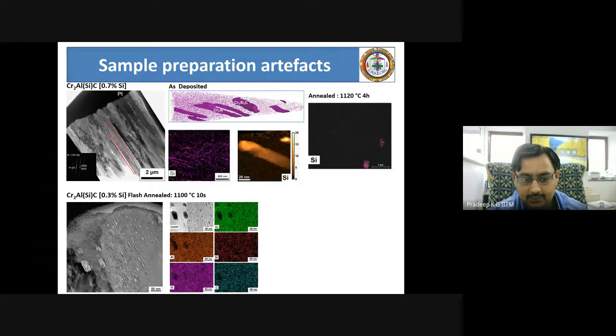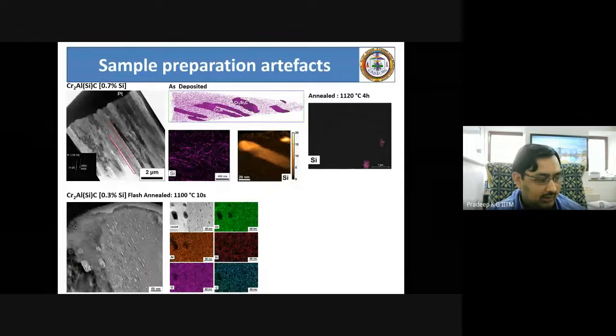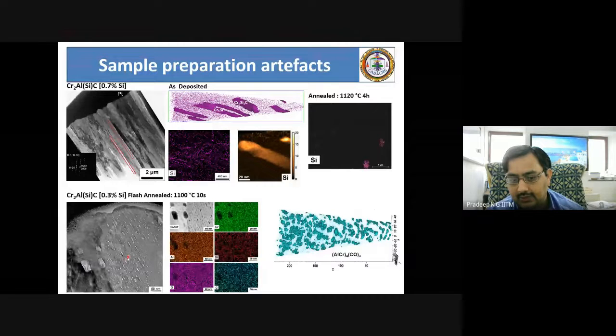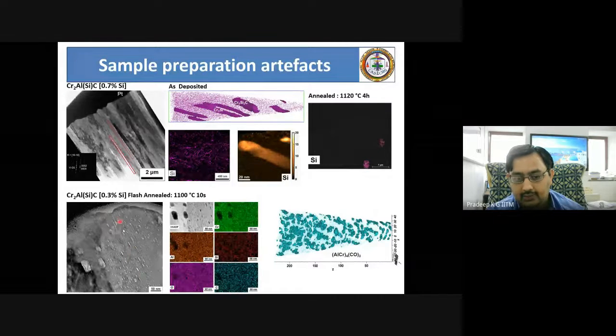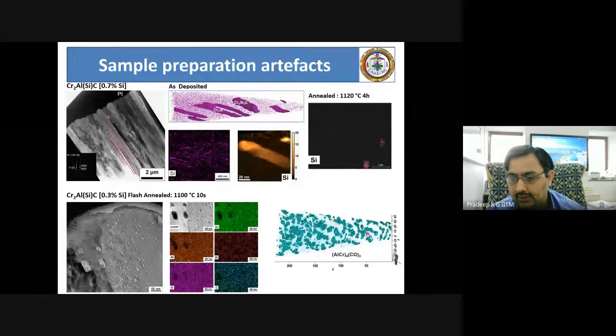Now, a similar example is at the bottom. As you see here, there are a lot of these nanoscale features visible in the microstructure of the same material. The EDS mapping indicates there is no signal coming out of these nanoscale features, which means these are all holes in an ideal way. But if you look at the same in an atom probe, you can see all of these nicely arranged columnar features visible in this order, where it is all rich in oxide content, based on aluminum chromium carbon oxide. That means when you get this material in the three-dimensional analysis, you are able to get some information at the nanometer scale, which is not possible in a composite microstructure imaged in a projected geometry.